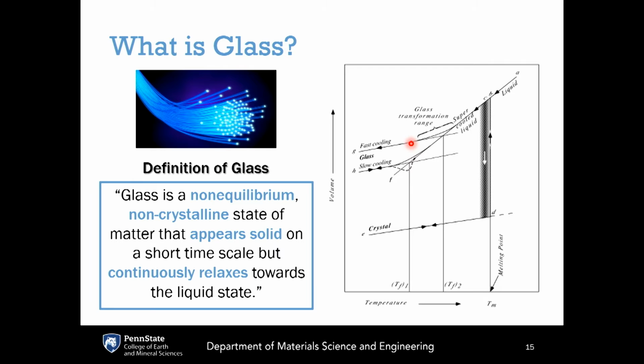So it combines some of the properties of solids with some of the properties of liquids. But it's also its own thing because of being out of equilibrium. So if the crystal is equilibrium, the supercooled liquid is metastable equilibrium. The glass is an unstable state. It is a non-equilibrium material. And if you hold it for long enough, it is going to be constantly relaxing, constantly trying to approach the supercooled liquid state. But this happens over very long time scales.